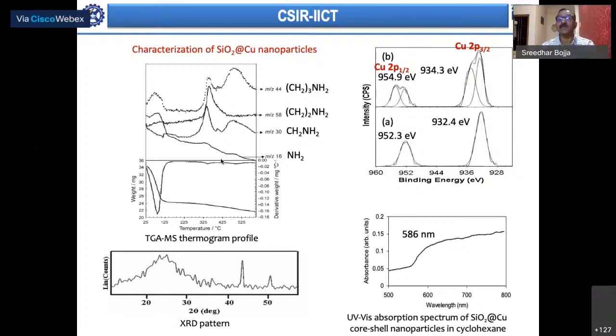Then we talk about copper. As I told you in my earlier slide, copper ions were reduced to copper metal. This is XPS, X-ray photoelectron spectroscopy, as I already mentioned in the beginning. XPS gives us information about the elements and their oxidation state. Initially, this peak at 932.4 electron volts is due to copper in its metallic form, and this was the starting catalyst.